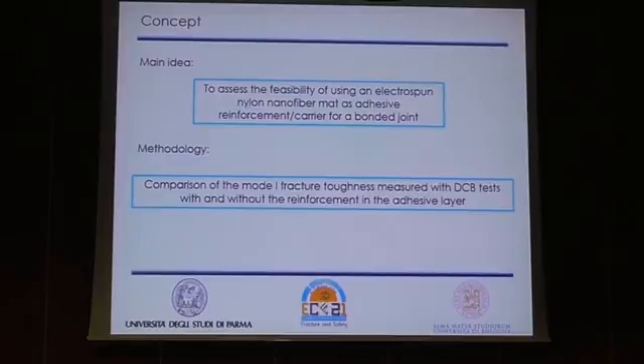Our idea was to try to use the same polymeric mat successfully used for composite laminate in order to reinforce even the interface and the bond line of the adhesive bonding joint, making the nanomat act as a sort of bridge effect between the adjacent layers and using it as a carrier for the adhesive. To assess the effectiveness of the procedure, the values of the mode 1 fracture toughness with and without the reinforcement were evaluated through an experimental campaign of DCB tests and were compared.